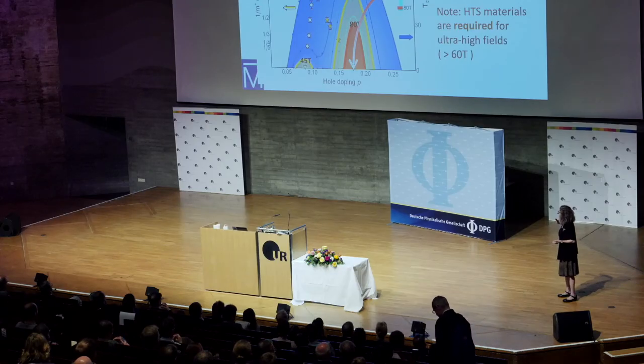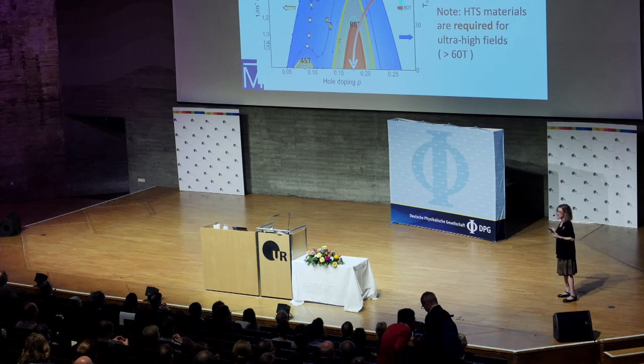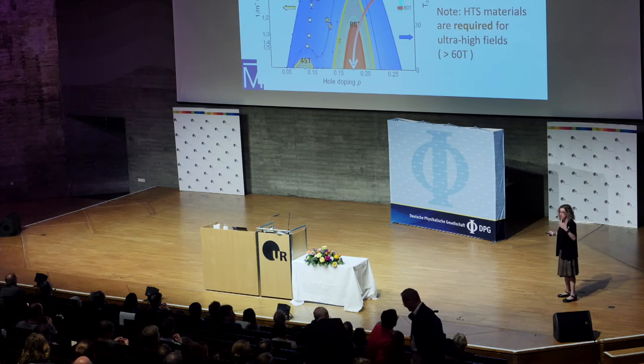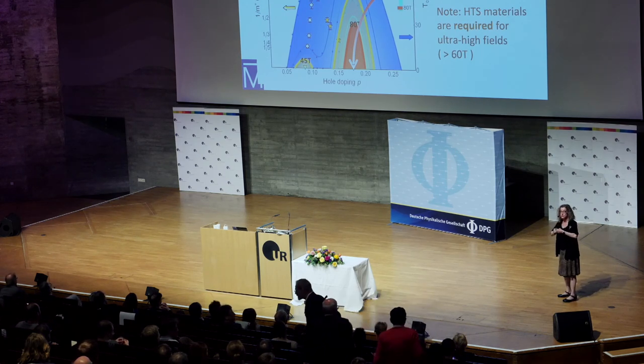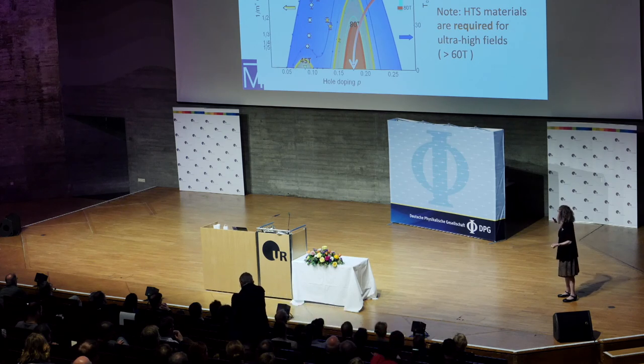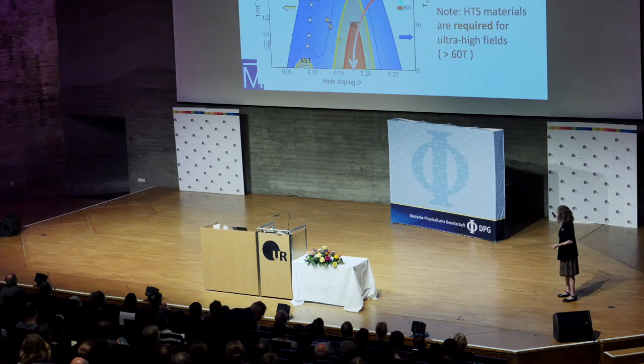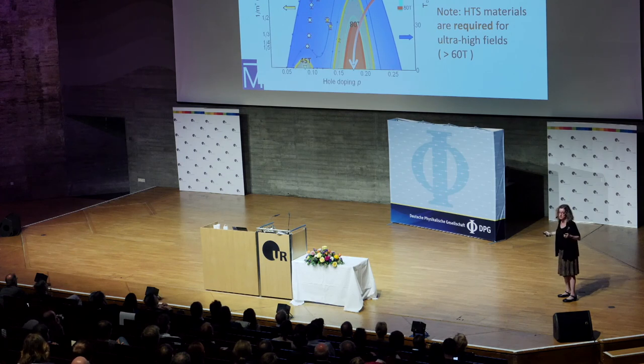This axis here is temperature, and this is some kind of thermodynamic variable. So in this case, the thermodynamic variable is changing the content, and you're increasing the number of holes. Underneath this dome is superconducting. So what has been seen in several experiments is you go to higher and higher fields, you break the superconductivity, and you can get further and further down. So at zero field, this is the TC, 90 degrees, and at some of these, you can push it down to 30 degrees, even at the optimally doped.